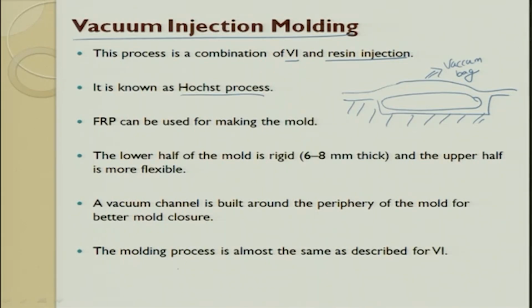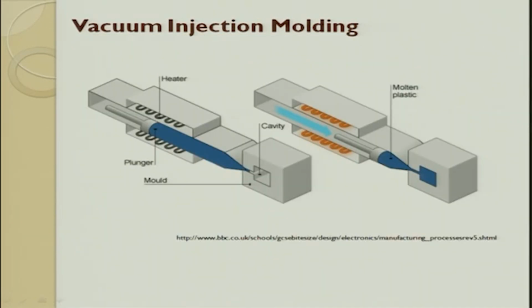The molding process is almost the same as described earlier. So, here what we do is, the vacuum channel is built around the periphery of the mold. So, all around you build a periphery and then you try to maintain a vacuum there. So, this is the heater, vacuum injection molding.